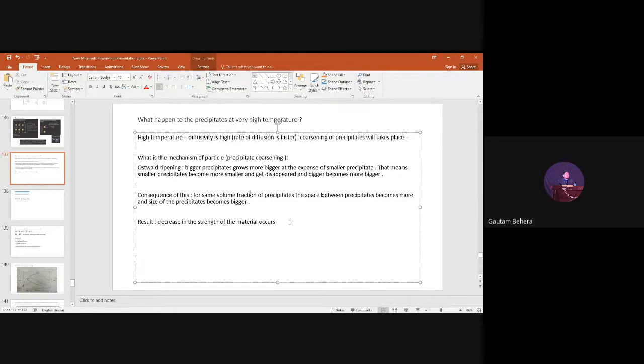Ostwald ripening is a mechanism in which the particles or the precipitates become coarser with time. So what is happening? You will be having smaller particles and bigger particles, or bigger and coarser precipitates. The coarser precipitates will consume the smaller, fine precipitates, and they become bigger. With time, the smaller precipitates will disappear from the matrix. We'll be left with bigger or coarser particles, which decreases the strength.